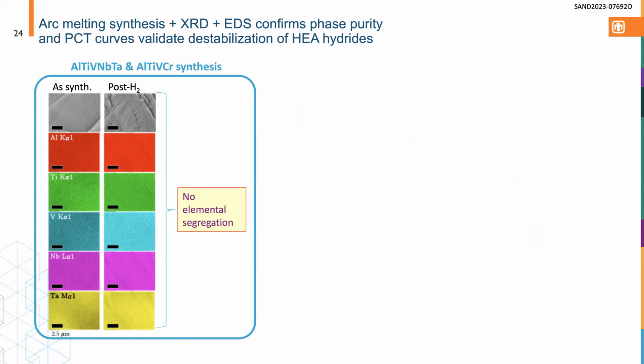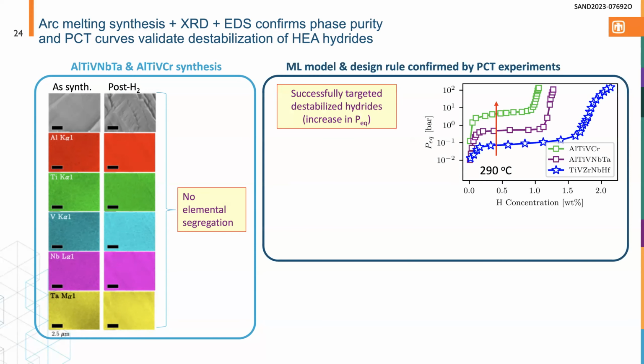So these are SEM EDS images of one particular high-entropy alloy we predicted, showing the fact that you don't have elemental phase segregation before and after hydriding. So essentially, what was a high-entropy alloy is still a high-entropy alloy after you go through the hydrogen cycling. Go to the next slide. Then you measure these materials. Again, here are the PCT curves. That massive increase in the plateau pressure corresponds to the materials we predicted on the previous slide.